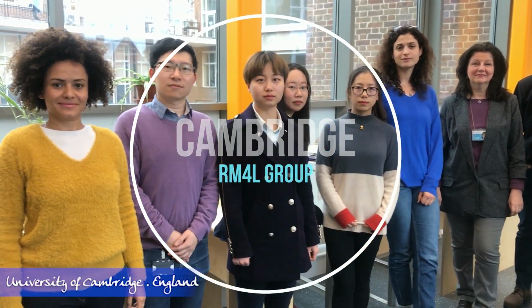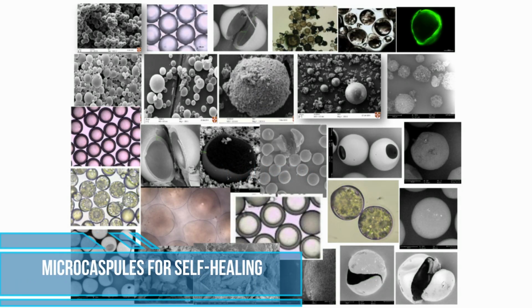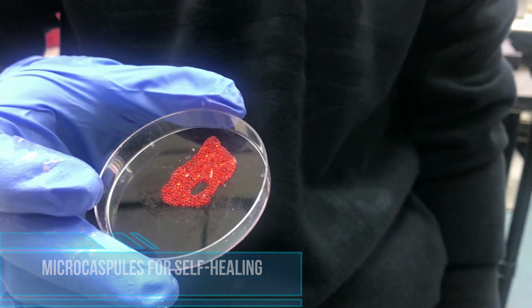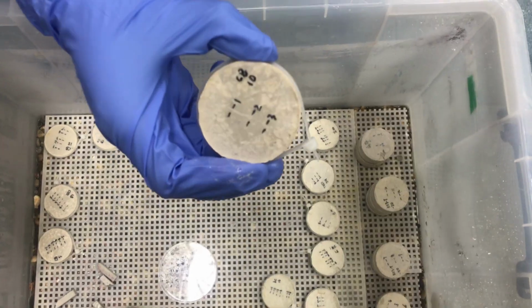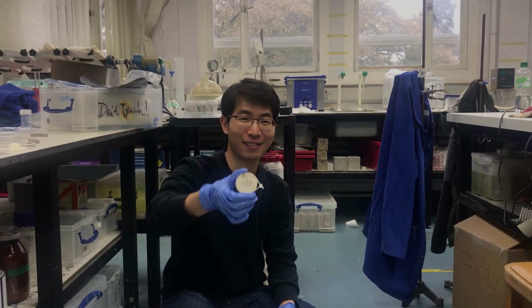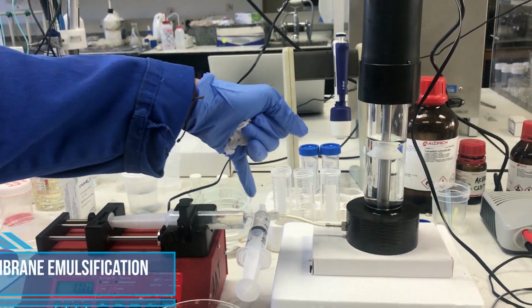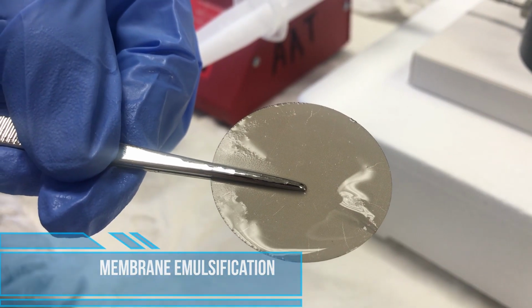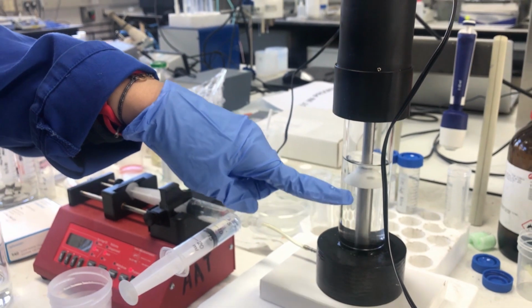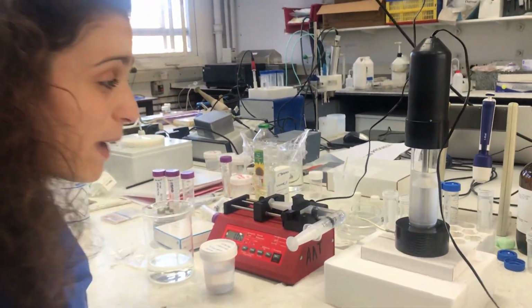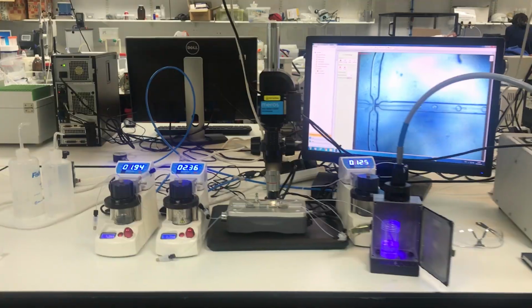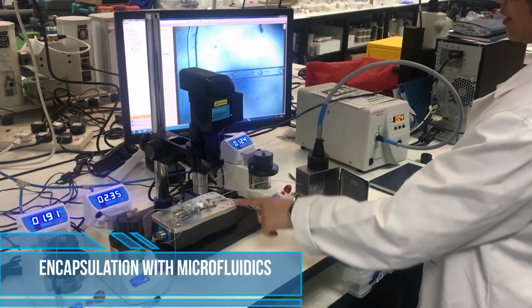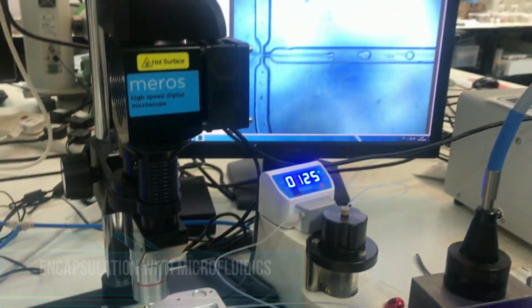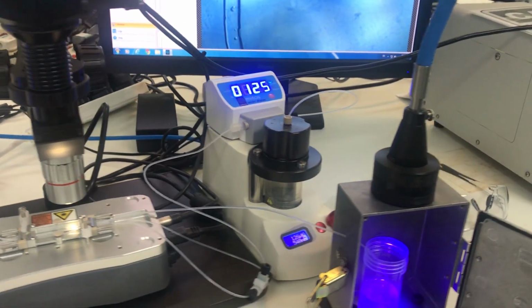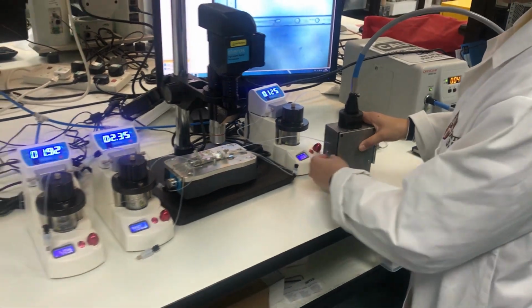The RM4L group at the University of Cambridge is working with self-healing systems for cementitious materials. Their group focus on producing and characterizing systems for autonomous healing in concrete and solid mix materials. They are exploring several ways to produce microcapsules, including membrane emulsification, where a membrane is used to form the emulsions which are then polymerized into capsules. In addition, they use microfluidics, a very controlled way of producing double emulsions, which are then polymerized using a UV light to achieve a core shell structure with control over the size and shell thickness.